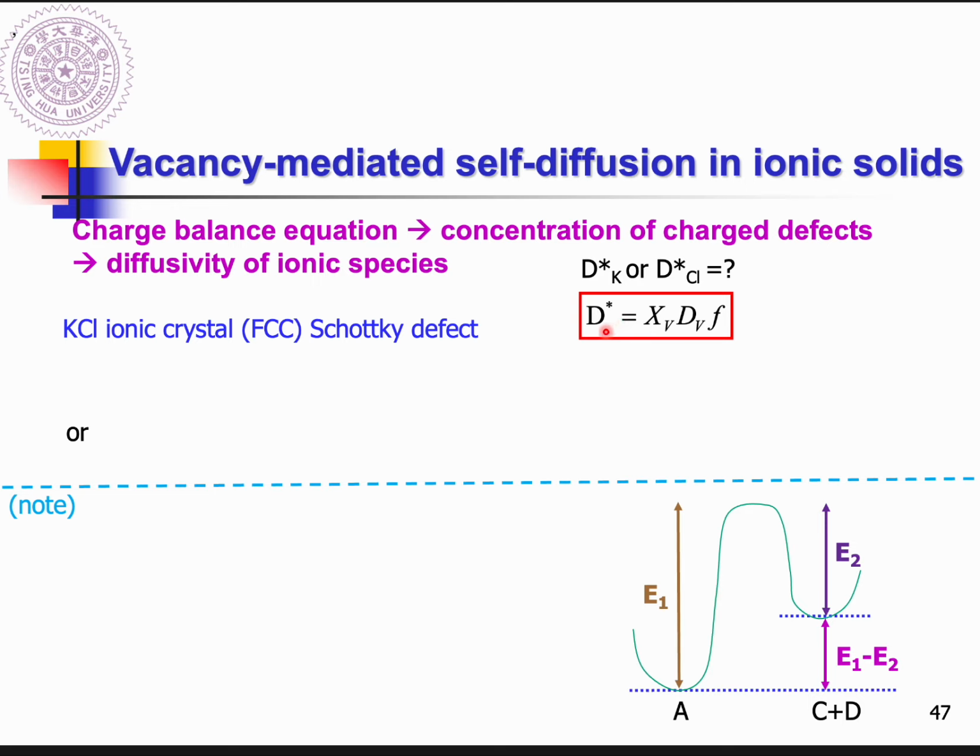For the vacancy-mediated diffusion, we know the self-diffusivity equals X_V, the vacancy fraction, times D_V, the diffusivity of the vacancy, and also the correlation factor f.